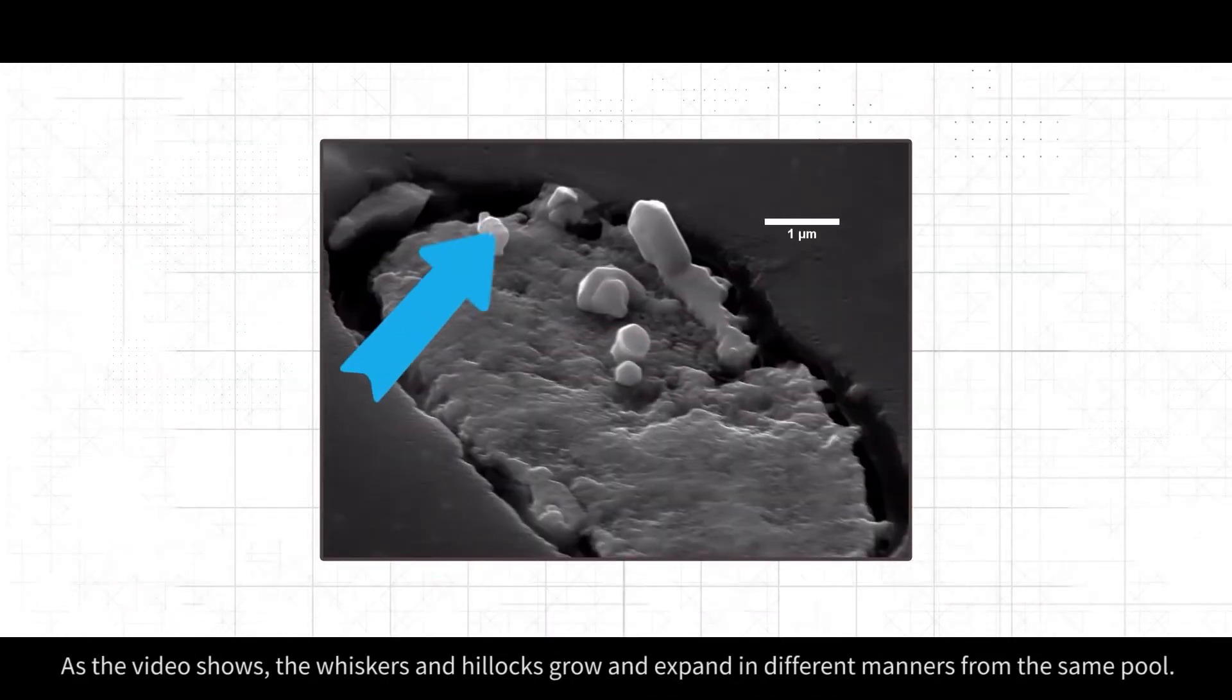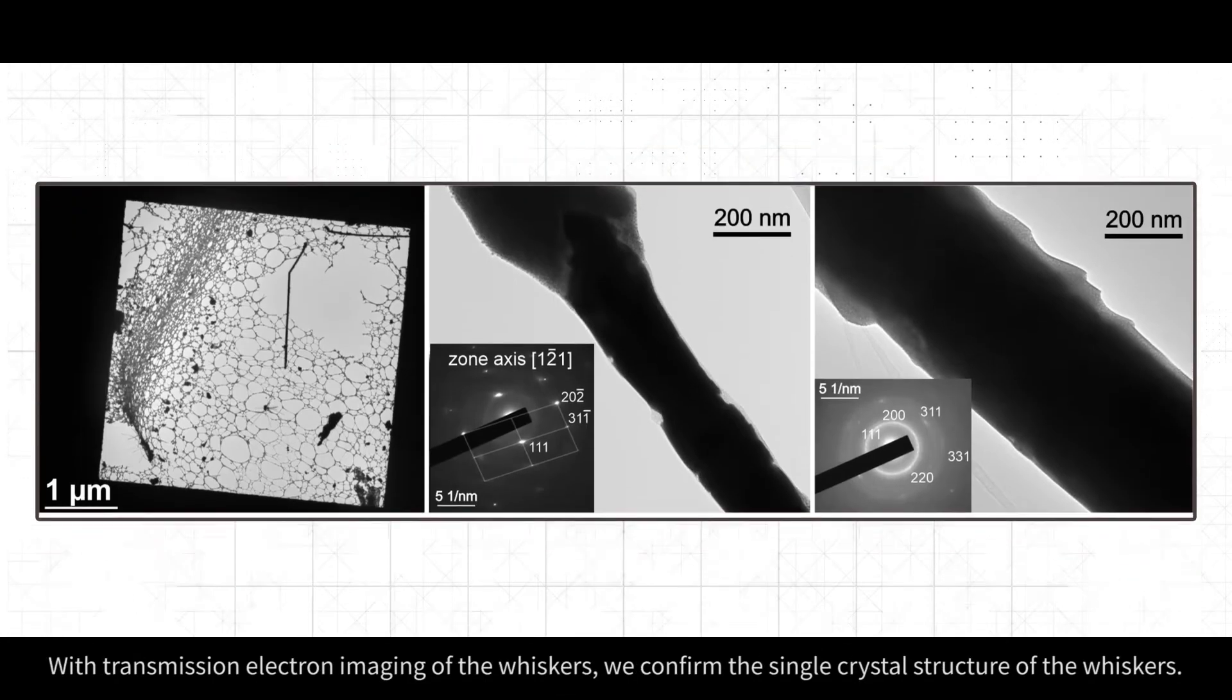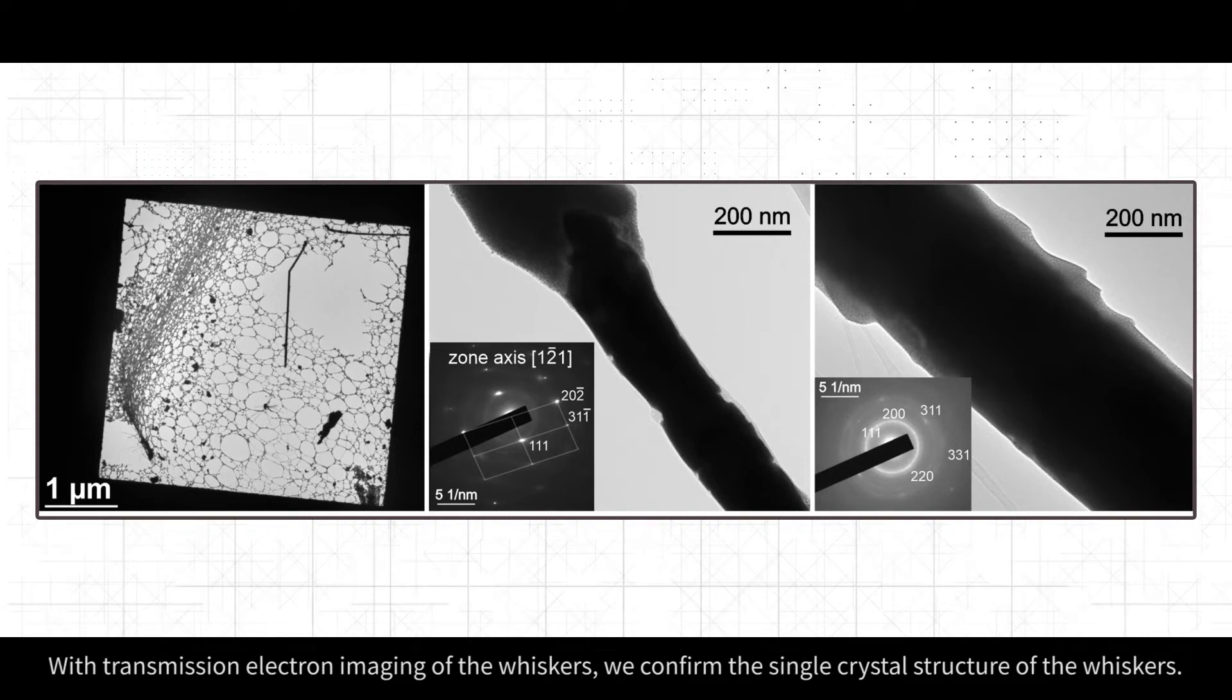As the video shows, the whiskers and hillocks grow and expand in different manners from the same pool. With transmission electron imaging of the whiskers, we confirm the single-crystal structure of the whiskers.